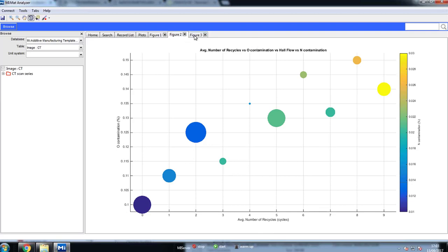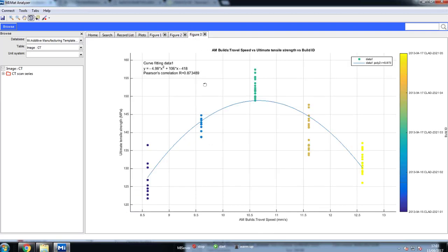Here's another example where we're looking at the number of recycling against oxygen contamination as well as nitrogen contamination. And finally, here's one assessment of a process parameter, travel speed, and the effect on ultimate tensile strength. And we can see the optimal travel speed is 10.5 to gain the highest UTS value.